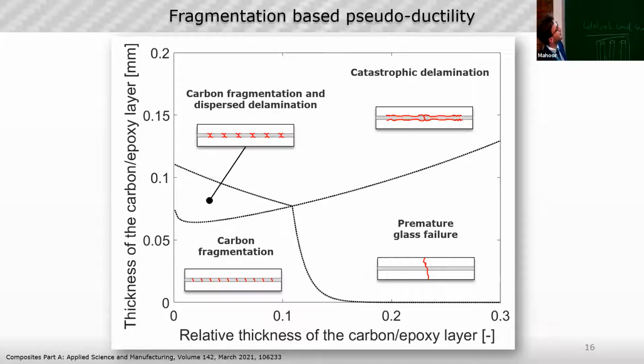But anyway, the delamination is created because, as I said, if we use too thick a carbon layer, it releases too much energy when it fractures, and the fracture toughness between the carbon and the glass is not enough to absorb it and suppress the delamination. So it happens that we have a catastrophic delamination, similar to the video previously shown by Dr. Sell during the experimental activity. And this is the region we want to have. According to the design and the thickness of the carbon layer, we want a thin carbon layer, and the thinner it is, the better the fragmentation behavior. So we can suppress the delamination together with that.